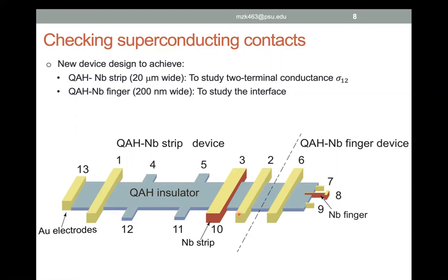And as you can see, I have 4 terminal, like normal gold contacts here. So that would allow me to exclude any contact resistance from the wires in the dilution fridge. So I can actually look closely at the exact value of the quantization here. And then I also made a niobium finger, which is around 200 nanometer wide. The reason that I'm using a finger here is because this finger geometry allows me to actually look into the interface between the superconductor and quantum anomalous.